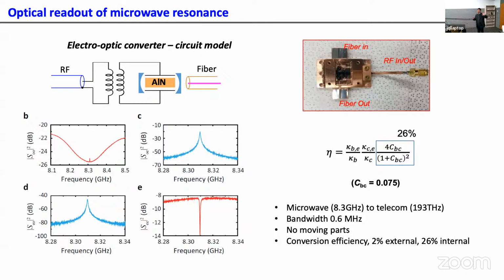And this conversion, again, is bidirectional, just as I showed you earlier with optical to optical conversion. You can build this S matrix for microwave to optical, with S11, S21, S12, and S22 measurements, as a standard process. You can quantify your cooperativity. And most important, through this optical reflection measurement, you can see this tiny peak. That's the microwave resonance, which you detect through optics. There's no microwave amplifier involved. So that's the microwave to optical conversion.